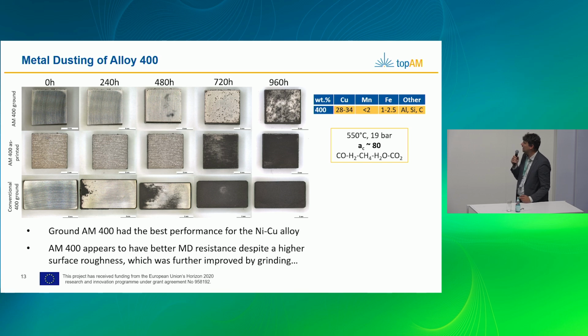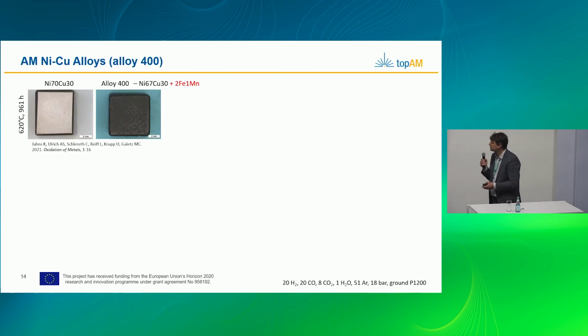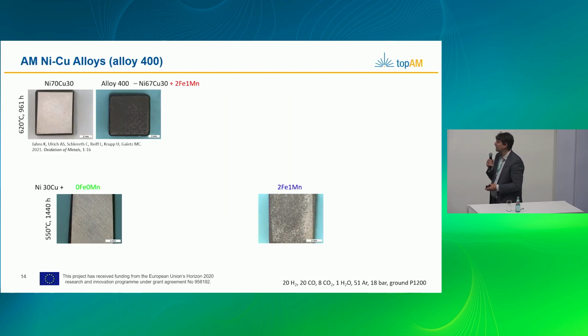After 960 hours, so almost 1,000 hours, the AM400 printed, in this case even as printed, is obviously better. It lasts longer. Also, finally, it turns black too, as does the ground material. So it seems that the AM has a better protective behavior, but obviously this alloy itself doesn't show what the lab alloys show when you just have nickel and copper. And the reason for that is that there's a little bit of iron and manganese in it. And we have seen before that iron can be quite detrimental.